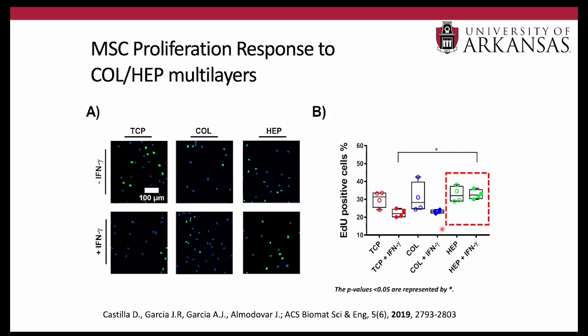So we did the same with our coatings. And what we observed was a slight decrease again in proliferation with our collagen terminated coatings, but on our heparin terminated coatings, we see no difference. We see that the cells proliferate just as well in the presence or absence of the interferon gamma. And so that was quite positive to us, because what we think then is that perhaps the coatings are interacting with the protein in such a way that it negates this anti-proliferative effect while maintaining the immunosuppressive properties.